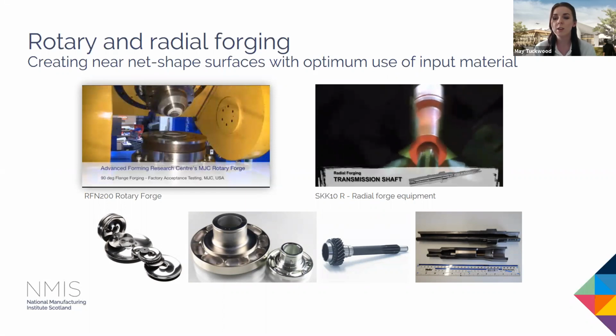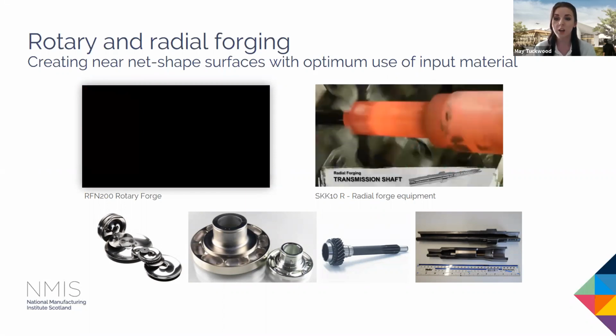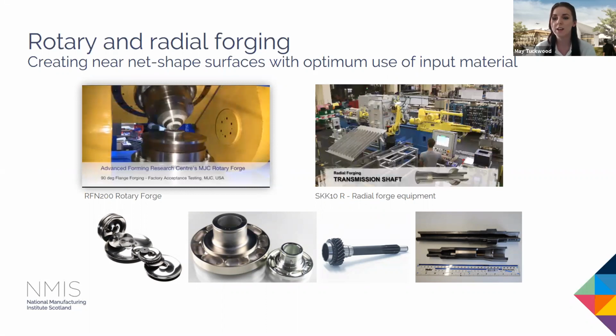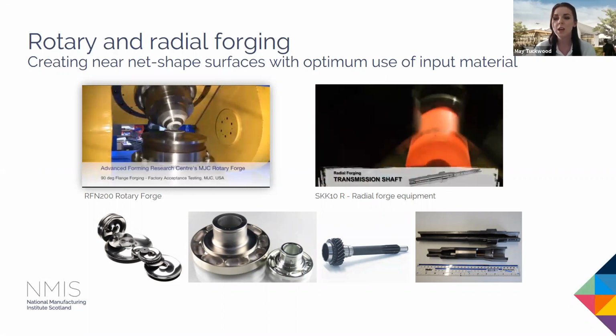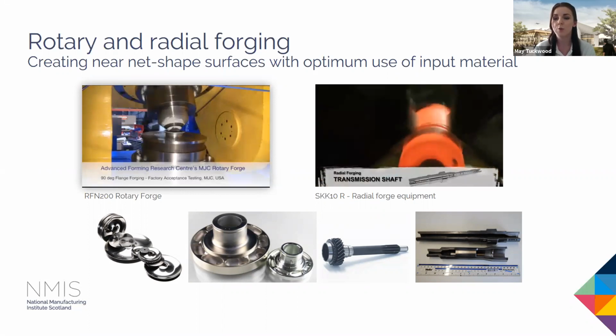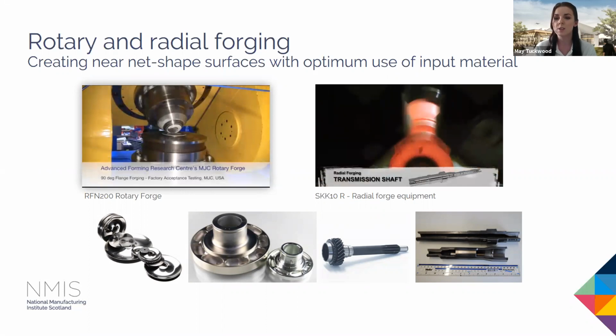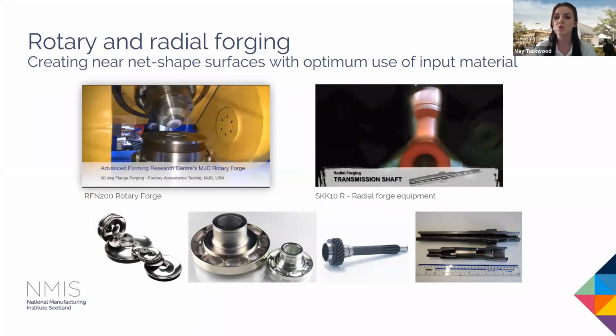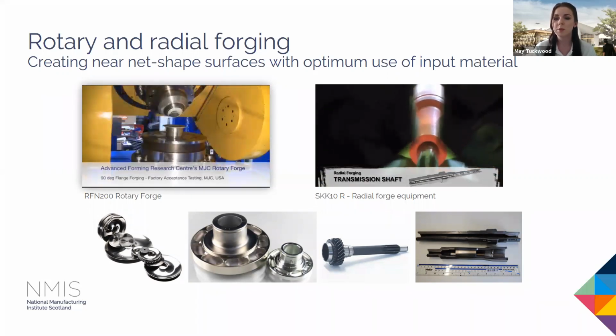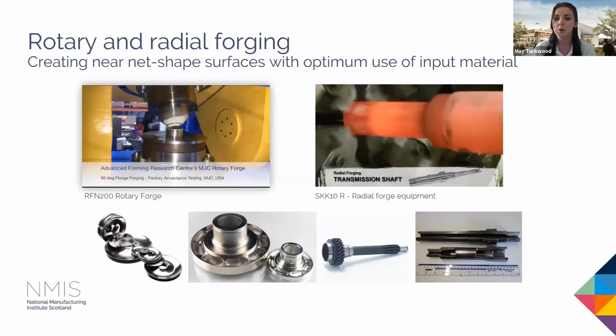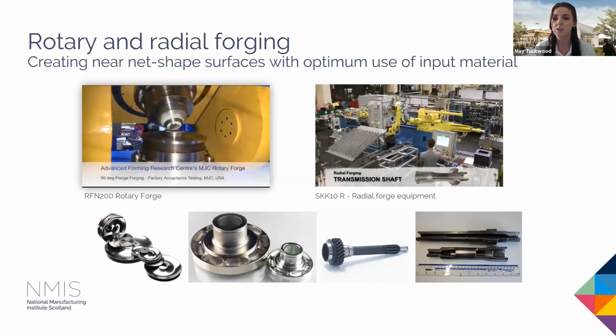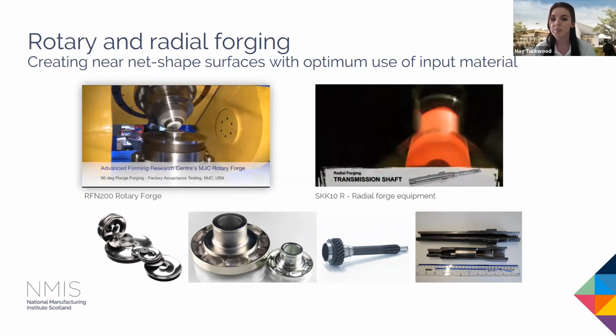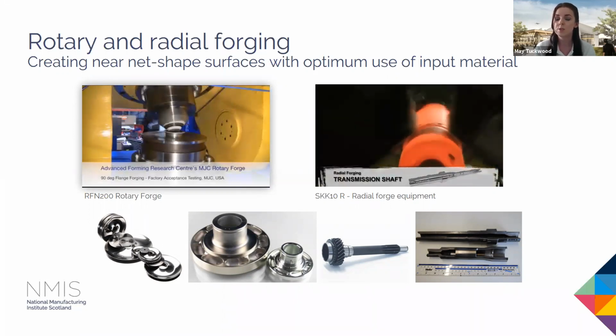So in this technology, similar to conventional forging, there is a lower die. However, the key differentiating factor here is that the upper die is conical. It's also nutating, and our machine's got a 45-degree nutation angle, which again gives us much more flexibility in terms of the component features that we can form. The key advantage of the conical tool is that the contact surface is drastically reduced. So approximately 30% of the workpiece is in contact at any one time, and as with the other technologies, it's continuously shifting, meaning that compared to your conventional forging routes, you're forming with much less force.